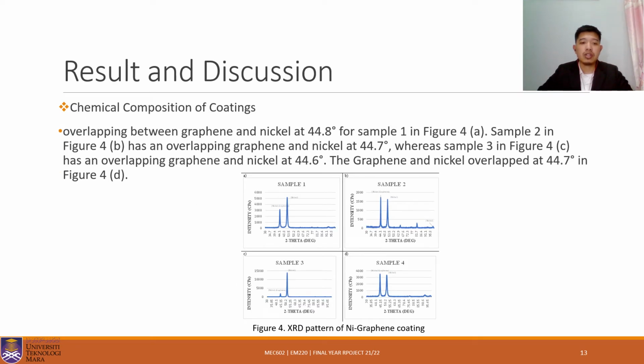Next is chemical composition of coating. Overlapping between graphene and nickel at 44.8 degree for sample number 1 in figure 4a. Sample 2 in figure 4b has an overlapping graphene and nickel at 44.7 degree, whereas sample 3 in figure 4c has an overlapping graphene and nickel at 44.6 degree. The graphene and nickel overlap at 44.7 degree in figure 4d.